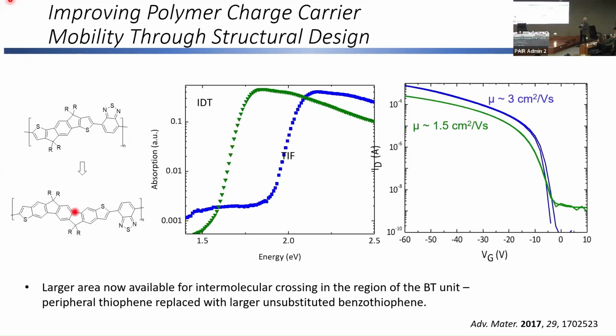In this case, this is a TIF BT. This is a slightly larger area for our short contacts. This is looking at the PDS spectra. You can see they're very low energetic disorder, but we've increased the carrier mobility by a factor of 2, just with this very simple change in being able to allow the backbones to assemble more easily.